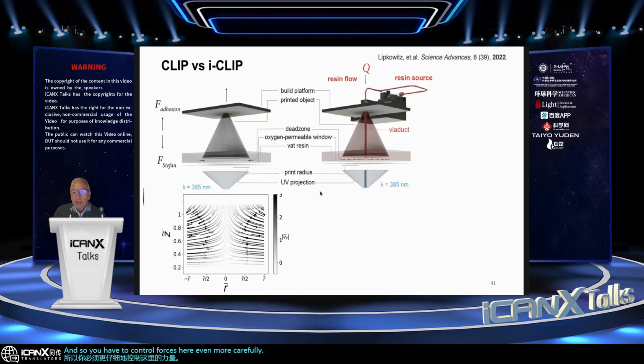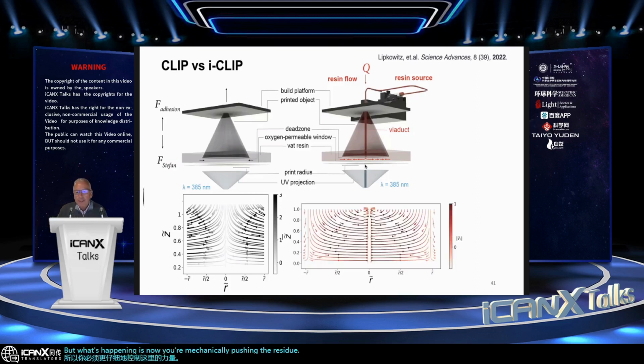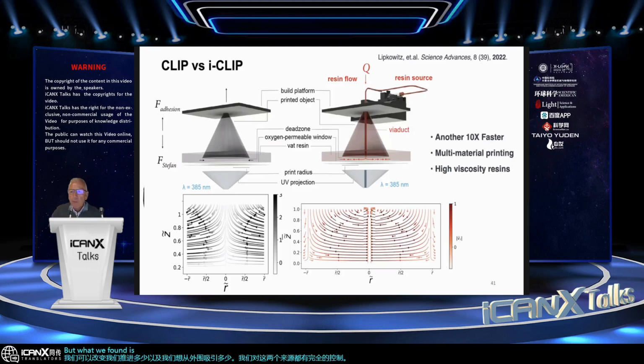But what's happening is now you're mechanically pushing the resin into this gap, and the fluid mechanics is completely reversed. We're pushing resin in and it's flowing out, and we can vary how much we push in and how much we want to draw from the periphery. We have total control of both sources of resin. But what we found is that we can now make the 3D printing process go another factor of 10 faster. We can actually have different resins coming in from different ports and do multi-material printing.